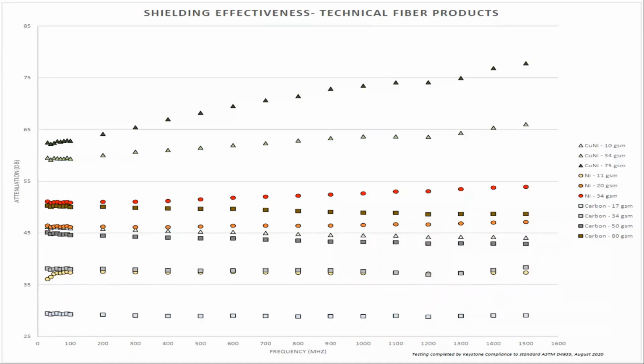I like to point out the red circles here in the middle, the 34 grams per square meter. You'll see here at the lower frequencies around 30 megahertz, you get about 50 dB. And at 1500 megahertz, or 1.5 gigahertz, you're around 55 dB. This is usually where I like to start customers with EMI shielding applications in battery enclosures.